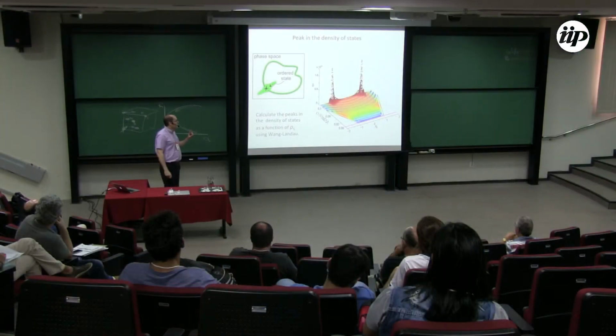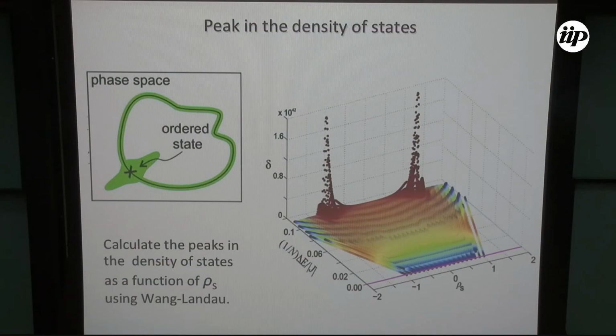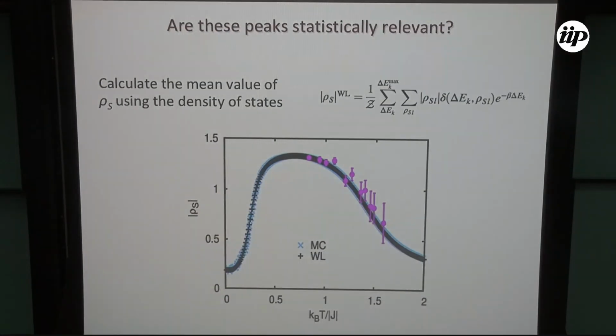You can say, okay, this is a peak. Is this statistically significant, or is it just a peak? You can check whether it's statistically significant. If I know the density of states, I can always use the partition function and calculate any observable. In particular, I can calculate what I expect to see for rho and compare that with what I see from the simulations. The light blue is the simulations, and the black crosses are what you get if you use the density of states and calculate the rho. You see that at low temperature they are one on top of the other, and these dots here are additional ways of calculating by chopping your density of states slightly and seeing whether, if you keep that peak, it is still statistically significant. And you see that it's a pretty consistent picture.